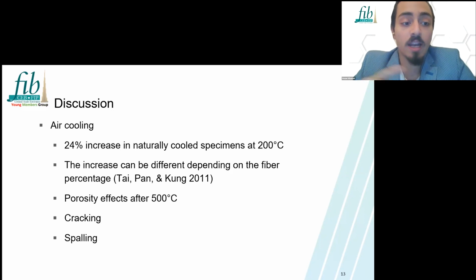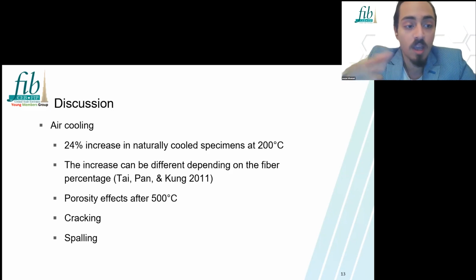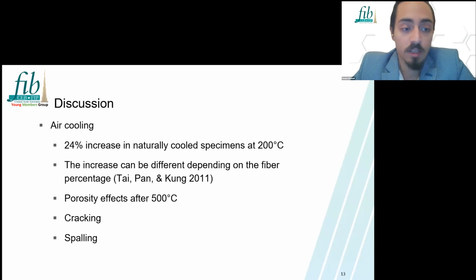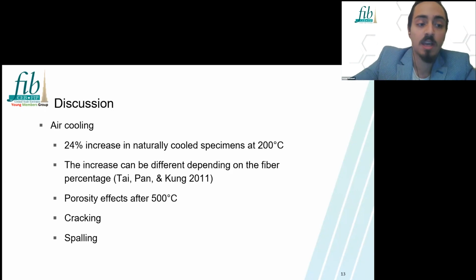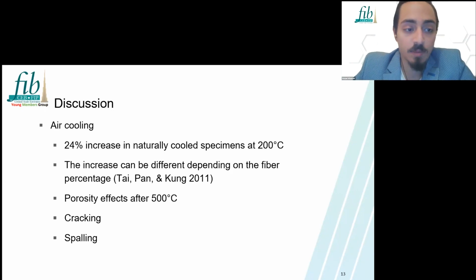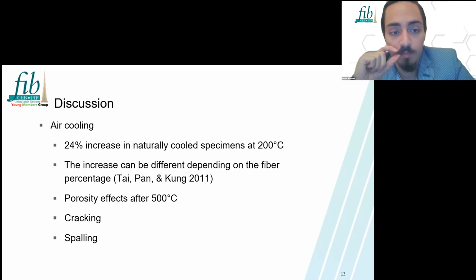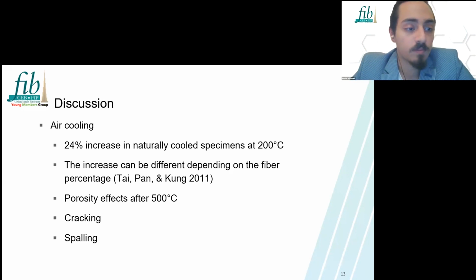This might be due to the highly porous nature that could reduce the effect of the additional binder. So there's a balancing effect between the higher porosity and lack of fibers. So we conclude here that the increase was obviously due to the combination of steel fibers and additional binder. As expected, steel fiber lightweight concrete showed hairline cracks at the early stages of heating and was more vulnerable to cracking, as we discussed earlier, because of the major internal stresses created by the elongation of the steel fibers at 500 degrees and more.